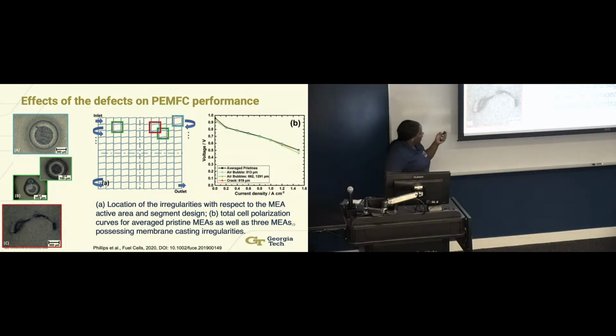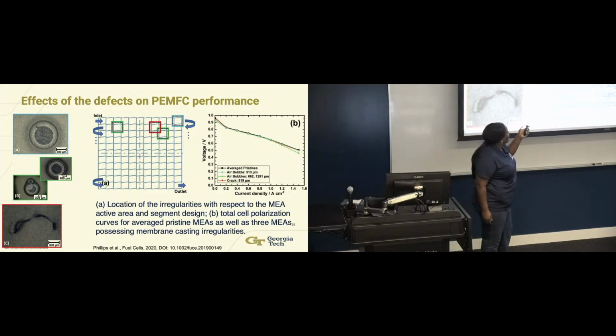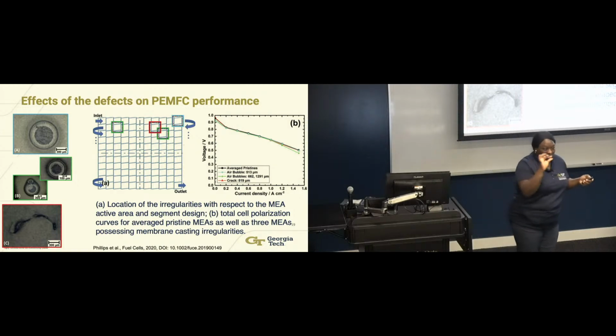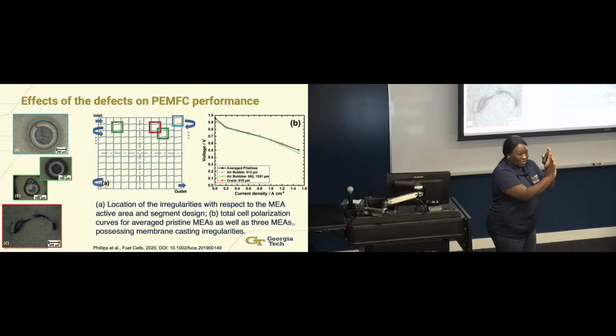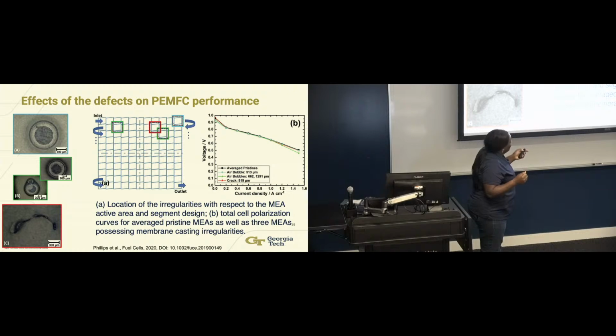So we made artificial and real samples. What they have is a segmented cell that has 121 unique points where they can test the fuel cell 121 times in one plate. So one fuel cell tested 121 times simultaneously. And since we knew where the various defects were, we could figure out what the influence is. What we were finding is that these are air bubbles, this is a crack, and this is an air bubble as well. This one is smaller, so these are two large and one small.